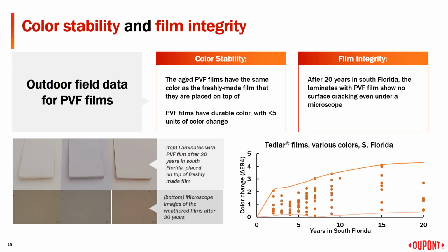So what we're seeing here is basically a similar representation of what we just looked at. This is actually Florida exposure testing that we've done for the last 20 years with all of our colors of film. So every color that Tedlar is available in, which ranges from nice bright whites to blacks, dark grays, dark browns. So you're seeing the aged film underneath and then the fresh film on top. Again, virtually no color change. And when we look at all of our films over time, they all change with a delta of below 5 units of color. About 3 to 4 is invisible to the human eye. So maybe our brightest colors, you could see something very slightly, but we would assume essentially invisible to the human eye. That's incredible. Look under a microscope too. We don't see any cracking, chalking, any kind of those surface issues that you get from long UV exposure as well. And again, this is 20 years in the Florida sun. It is. And moisture. Yeah, the harshest environment there is.